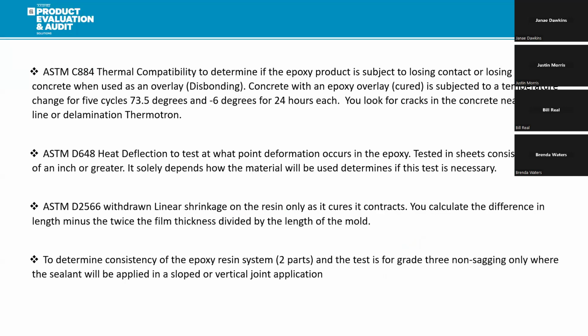And I'm going to turn this back over to, well, I want to talk to you a little about other tests that some DOTs don't do. Third party might do them. ASTM C884 with thermal compatibility is used to determine if the epoxy product is subject to losing contact or losing adhesion to the concrete when it's used. Concrete with an epoxy overlay is cured, and is subject to temperature changes. A lot of the states are cold weather states, so it cycles through freeze, thaw, freeze, thaw, freeze, thaw, and then heat, heat, heat. So you want to cycle this through 5 cycles at 73.5 degrees and -6 degrees for 24 hours each. So you can imagine, you have to do this for 5 cycles. It takes a long, long time to do this test.